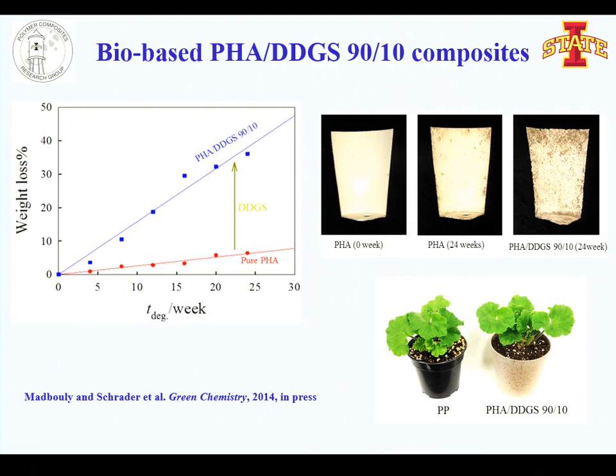And this is one of the most interesting data. This is our paper, which was just published in Green Chemistry. Just by adding 10% of DDGs to the PHA, we found that the degradation increased dramatically. With just 10%, we reach about 40% after 24 weeks, which is very interesting. And the plant can grow as well as the control material. There is no toxicity.